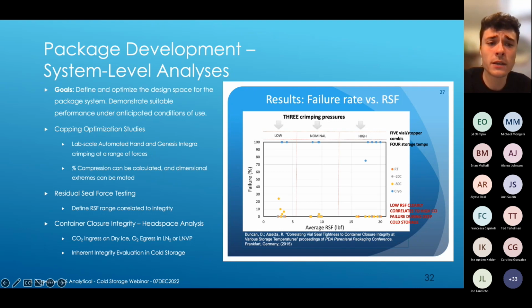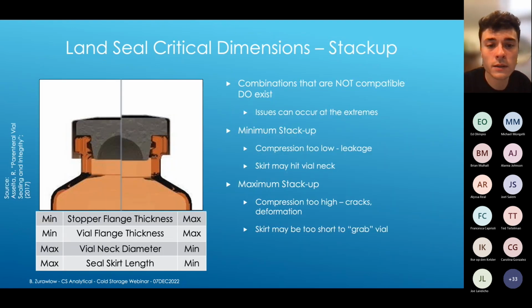Residual seal force testing is often incorporated into this package development phase and provides a way to correlate leakage and compression back to RSF. For those who aren't familiar, residual seal force is essentially an indirect measurement of how much force this stopper is applying to the top of that vial. And that's going to be a function of how compressed that stopper is, and ultimately that can be correlated to whether or not that vial has an integral seal.